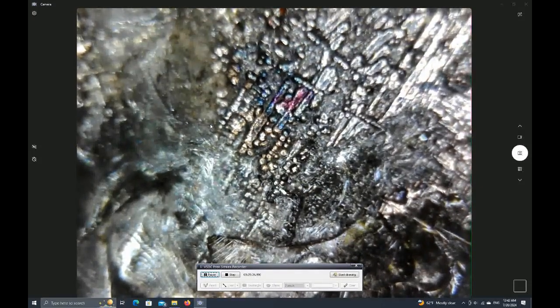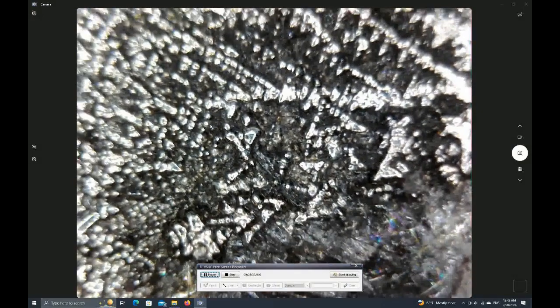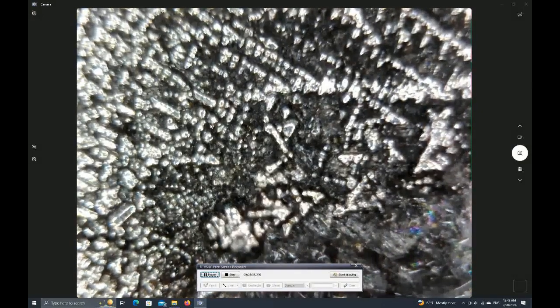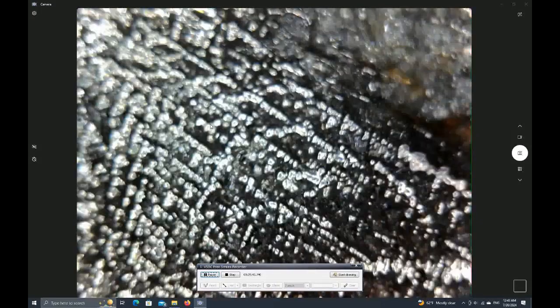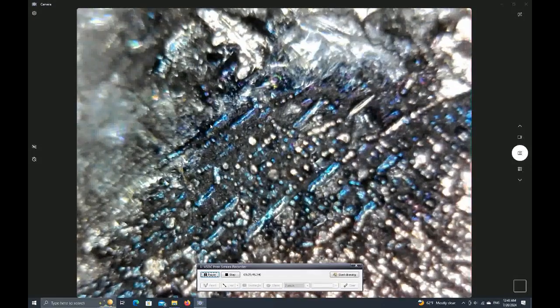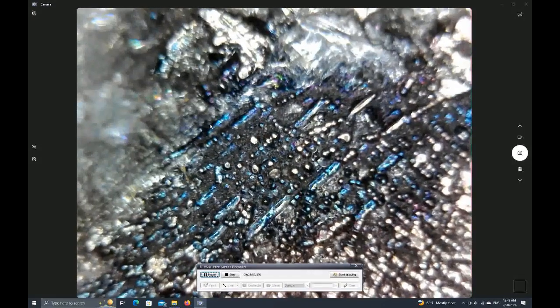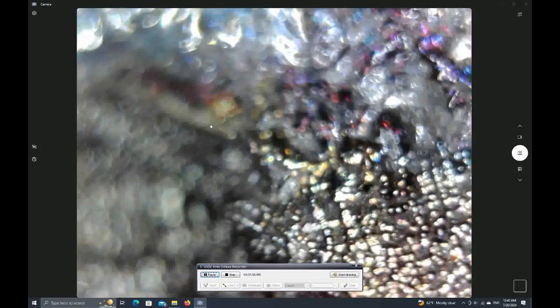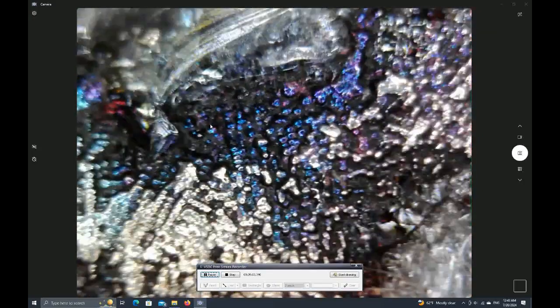But in the meantime, general rule of thumb with forging crucible steel ingots or Wootz steel ingots is that you weld on a bar to use as a handle to the top of the ingot, because it's widely assumed, or I guess known, that the top of the ingot is where all the nastier crap, the impurities, kind of migrate with slag, essentially. Like any other molten metal, the slag always floats to the top, and the good steel, the good material, is in the bottom. So we won't really worry about the pockmarks too much. Let's zoom in a little more, shall we?